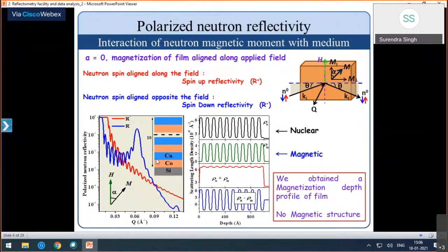The resultant scattering from that, the interference fringe comes when sine square... fringes due to scatterers placed at the same distance. So if you see, between two Bragg peaks, there should be some oscillations, maxima and minima, in the case of multi-layers.